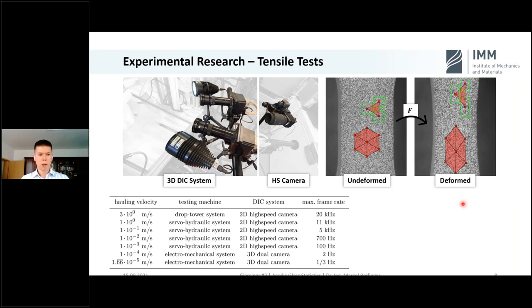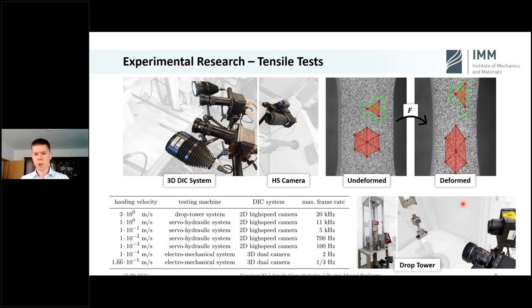Common ones like the hydraulic system or the electromechanical system, and an unusual one like the drop tower system, you can see in this picture here. You have a fork dropping from the top, and our specimen is down here on the lower side. And this fork, see here on the corner, it will drop down and catch the specimen on the downside and suddenly deform the specimen, and our camera system will track the deformation.